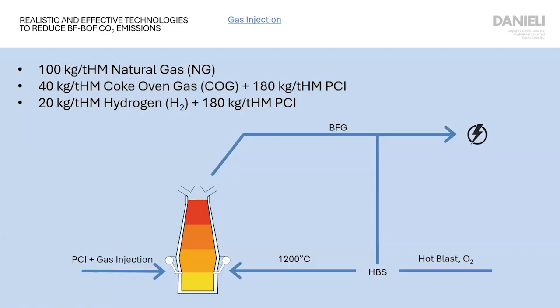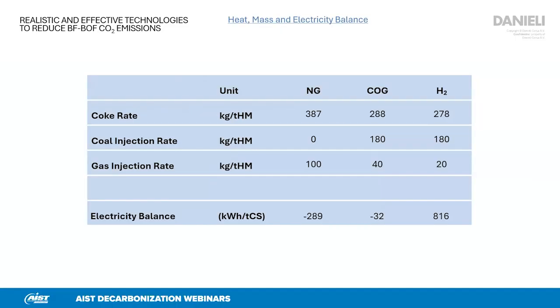And experimental blast furnaces have already demonstrated capability to inject much higher levels, even beyond 40 kilos. But there are some setbacks of doing this on the heat balance. So we've been assuming a moderate amount of 20 kilos. Let us first look into the KPIs of the blast furnace when comparing natural gas, coke oven gas, and hydrogen.